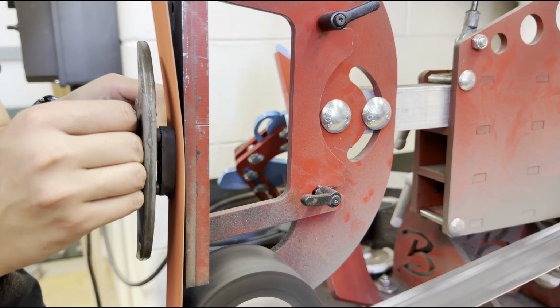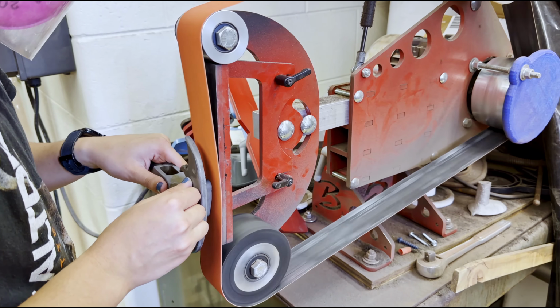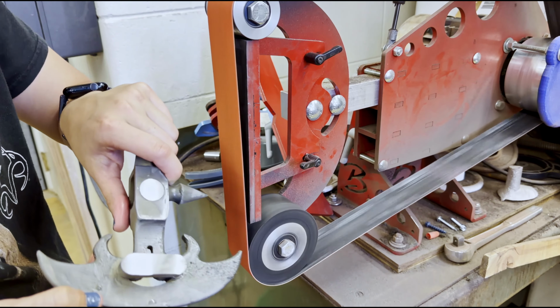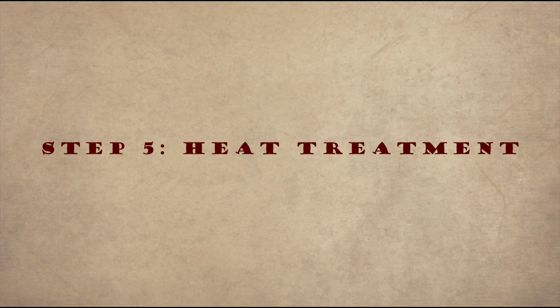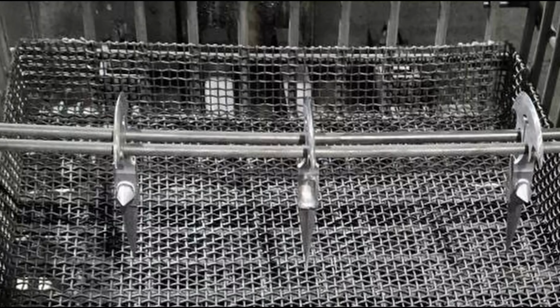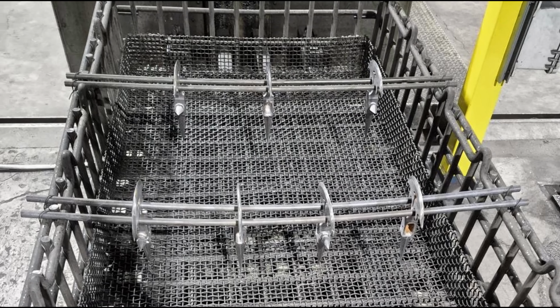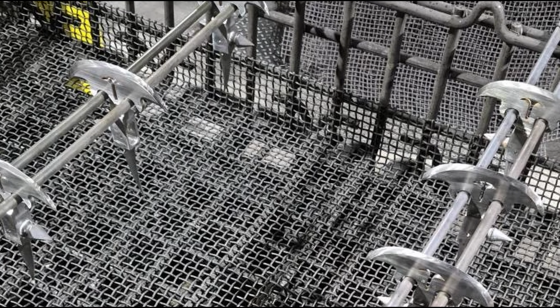By performing a majority of grinding in a softer as-cast condition, we minimize the risk of overheating the material and preserve the desired microstructure. The axes then underwent a carbon restoration followed by a mar quench in molten salt to produce a uniform hardness of 52 HRC.